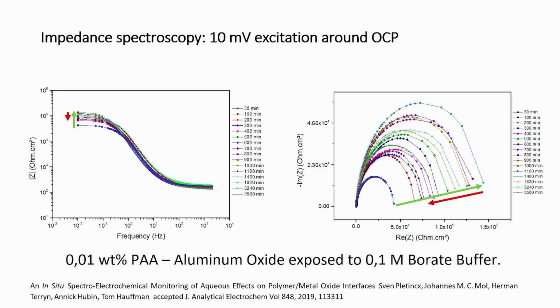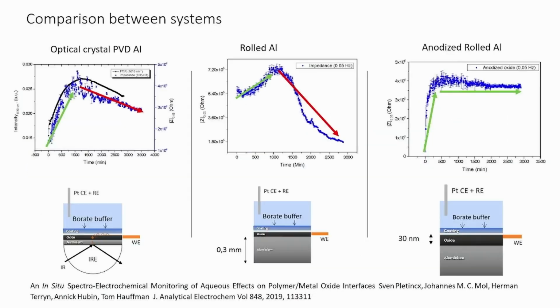If you measure a thin film, so this is what I'm showing here. This is in fact the in situ infrared system, where these measurements are the infrared measurements showing you the carboxylate bond, which is formed and destroyed as a function of time due to the presence of the water. So water is in the beginning facilitating the bonding and later destroying the bonding. And as you can see, we have a correspondence with our impedance measurements.